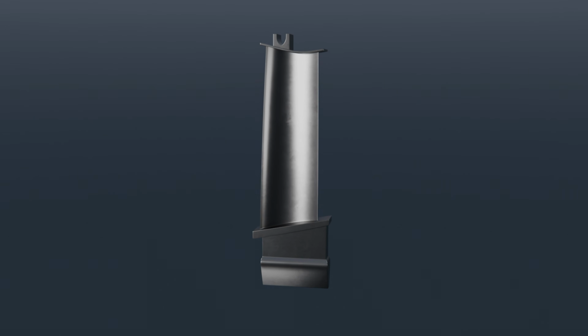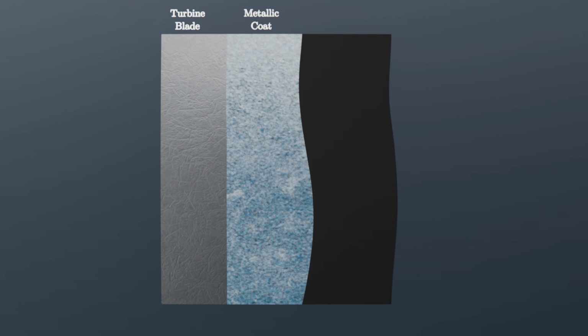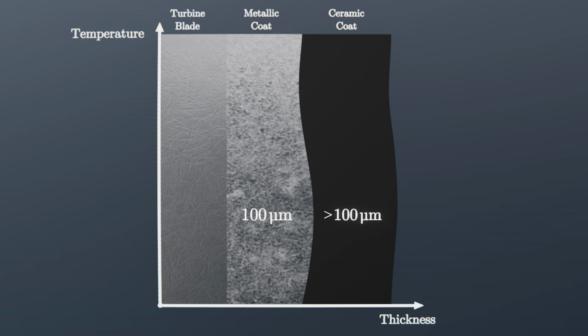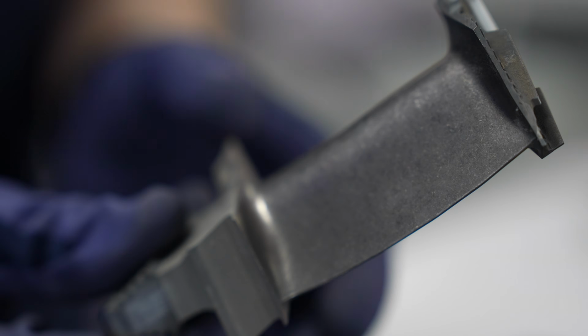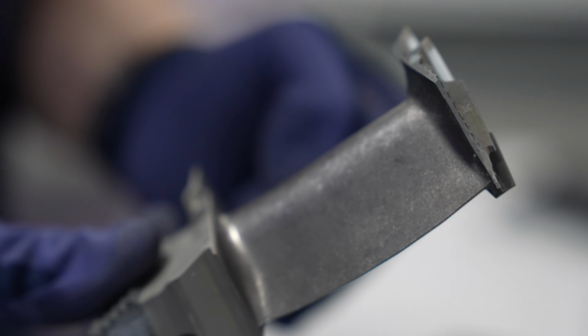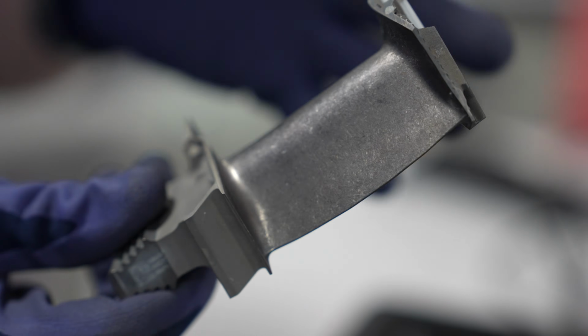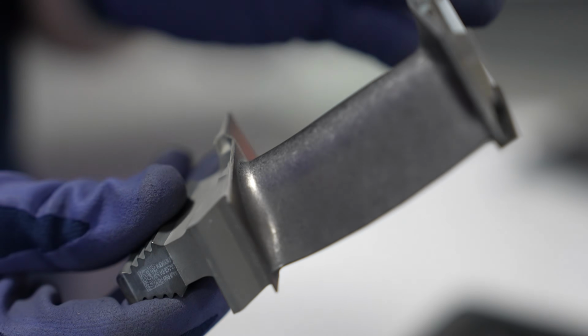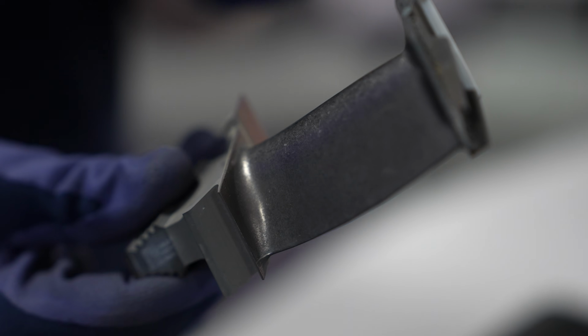So every turbine blade is also coated with 2 protective layers. First, a thin metallic bond coat that resists oxidation, and then a ceramic top coat. Even though it's only about 1/4 millimeter thick, this ceramic coating can keep the metal beneath it 100 to 170 degrees cooler than it would otherwise be. And this is the final barrier that stops the blades from melting.